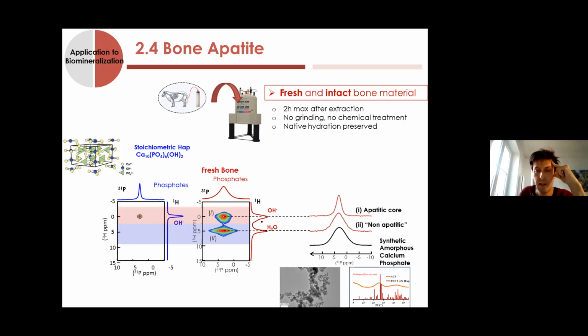And then you can extract the specific phosphorus resonance by taking just the slices of the 2D. You see that the positions are almost the same, but the line width and the general shape of the lines are different.